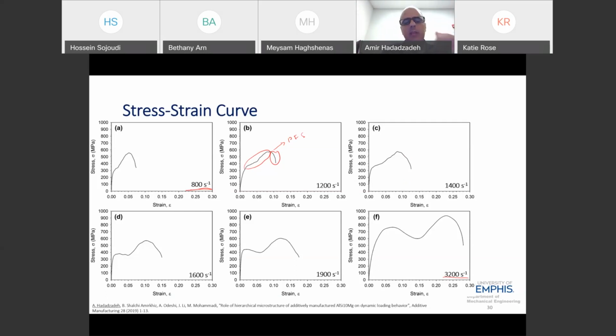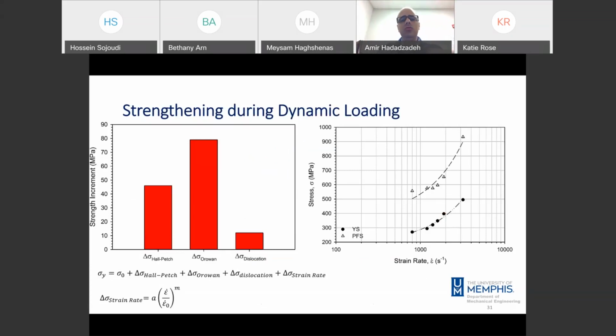But in the bottom graphs, we see a different behavior. So after that initial hardening and reaching the first peak flow stress, now we have a softening in the material. So this softening regime in the material is observed, which is followed by the second hardening regime up to the second peak flow stress. So these are two different types of material behavior.